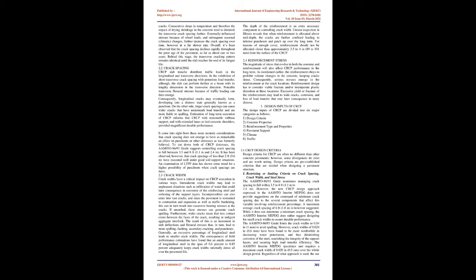to spalling. Estimation of long-term performance of CRCP shows that CRCP with reasonable subbase support, and with extended lanes or tied concrete shoulders, provided excellent durable performance. It appears from these more recent considerations that crack spacing does not seem to have as remarkable an effect on punch-outs or other distresses as was formerly believed.